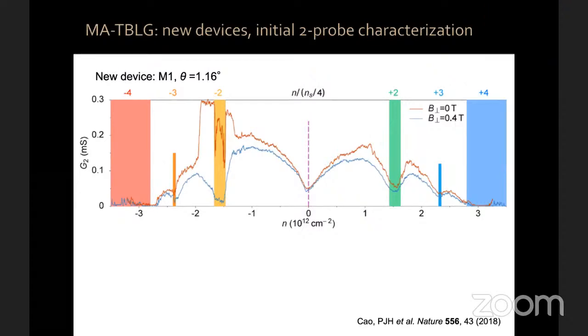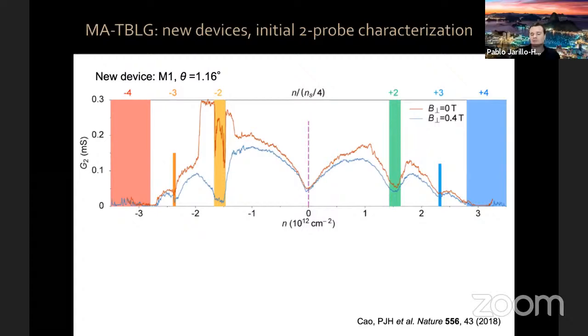Do you know if, when you reach the magic angle, the distance between the two layers changes? Can you measure that? That's a very interesting question. As I mentioned a little earlier in response to a different question, there are relaxation effects that take place at these angles. The smaller the angle, the larger the relaxation effects. The relaxation effects are not only in XY, but also in the Z direction. So theorists have now calculated the displacement in the z direction as a function of angle, and they see that it's finite, and that it affects the electronic structure at the single particle level. If it affects the electronic structure, it may likely also affect correlations. So this is something that experimentally has not been investigated.